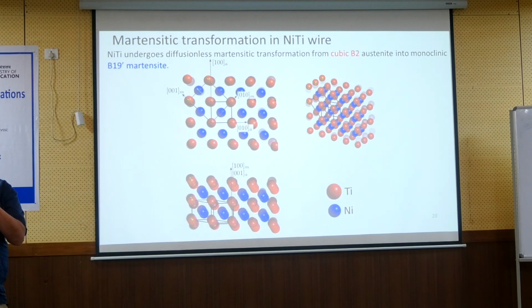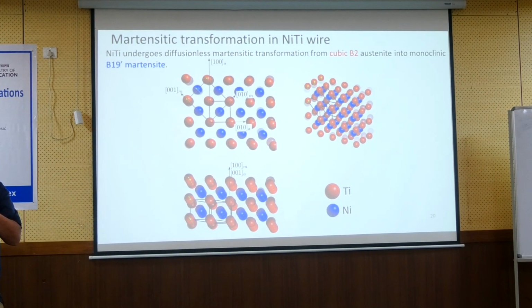the calculations are done for no stresses. But under stress, your cubic is changing into the orthorhombic shape because elastic deformation expands it a little bit. And also, you might have some plasticity. Every experiment tells us that at high temperature we have plasticity. So it's appealing to consider some kind of plastic deformation which can be added to the transformation. And this idea is shown here.